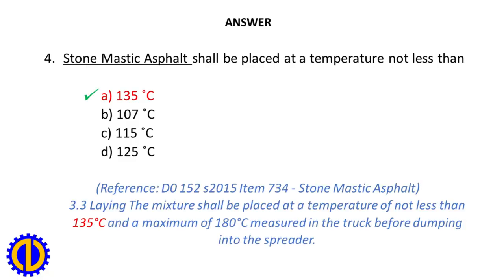Answer: A. 135 degrees. Reference: D.O. 152 S. 2015, Item 734, Stone Mastic Asphalt. The mixture shall be placed at a temperature of not less than 135 degrees Celsius and a maximum of 180 degrees Celsius, measured in the truck before dumping into the spreader.